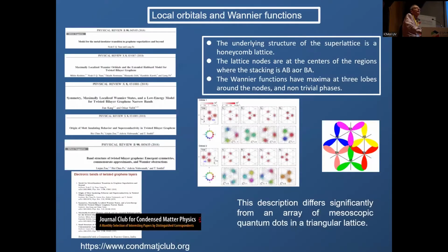And all these approaches and more have been used in connection with twisted bilayer graphene. Let me also mention that in order to have flat bands, a typical way you study them is by defining localized Wannier functions, and then you go to a local basis and you describe the interactions in a local basis and so on. There are very subtle problems when you try to define your Wannier functions in twisted bilayer graphene. That's called the obstruction. And this is now a whole new field in topological materials: which materials are obstructed and which materials are not. And one of them is twisted bilayer graphene.